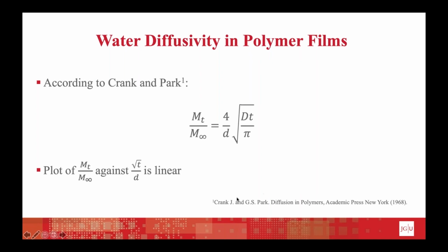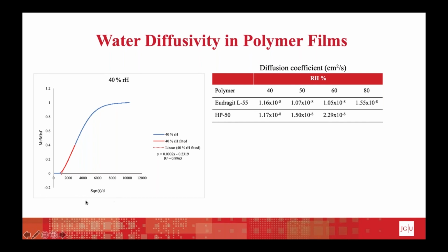And so if we plot M_t divided by M infinity against the square root of t divided by the thickness, we should get a linear plot of our sample. This can look, for example, like this here. And from the initial part of our graph, from the slope, we then could calculate our diffusion coefficients. And as we can see, in both polymers they are quite low, with 1.5 times 10 to the minus 8, for example at 80% for the Eudragit L55 polymer.